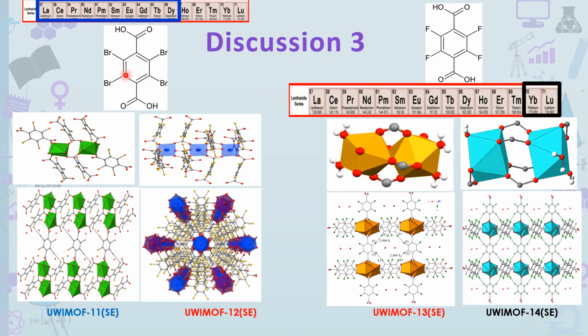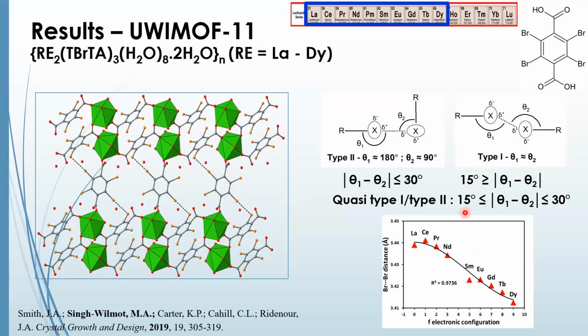When we change the tetrabromo to tetrafluoro, we formed different structures. In fact, over here, I'm showing you the tetrafluoro structures. Tetrafluoroterephthalic acid gave us UWI-MOF 13 and UWI-MOF 14 for the very small lanthanides, ytterbium and lutetium. And we were interested, like I said, in these tetrahalo ligands because of the abilities for halogen to halogen interactions, which are still being exploited in supramolecular chemistry.